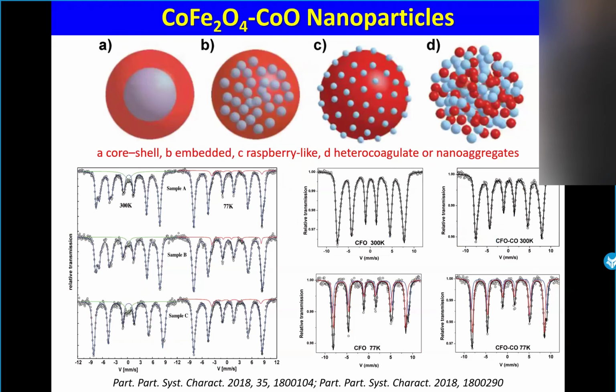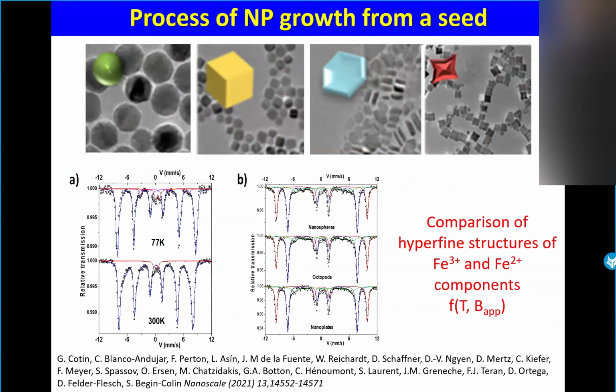As I mentioned, Nader will discuss other systems this afternoon. But now there is a kind of zoology for nanoparticles. You can see core shell, embedded, raspberry, hetero, and so on and so on. I have studied many of them. By using Mössbauer at different temperatures, and in addition applying an external magnetic field, it's possible to get very interesting information. Here, for example, the growth of particles.